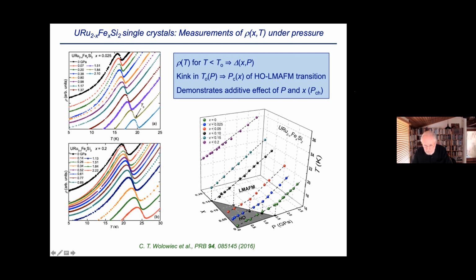And then it's a little bit hard to see here, but there's a distinct kink as you go into the antiferromagnetic region. And then you can take this composition of iron, 0.025, and you see that the kink occurs right here. And so you can extrapolate it down to the concentration-pressure plane and find a point here. And do the same thing for successively higher iron concentrations. And then the projections define this plane here, which is the region in composition versus pressure in that plane within which hidden order occurs. And then in this other region, you get large moment antiferromagnetism.